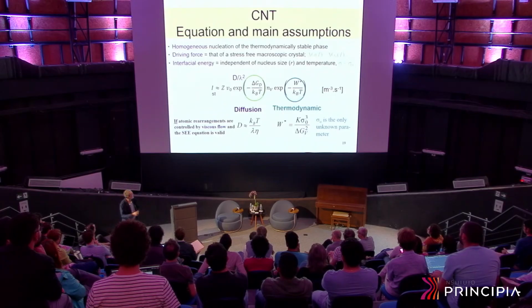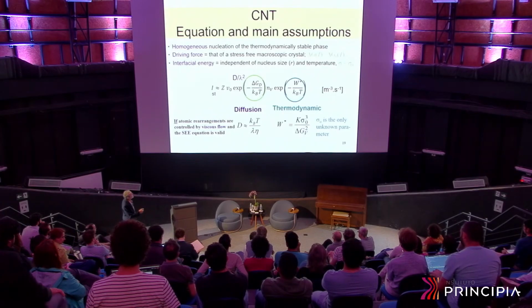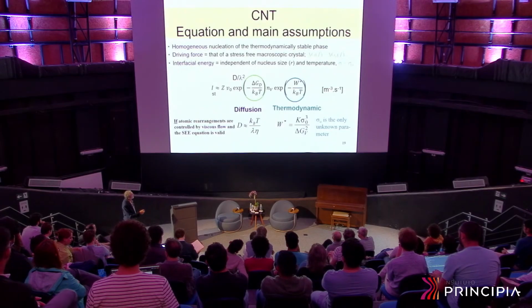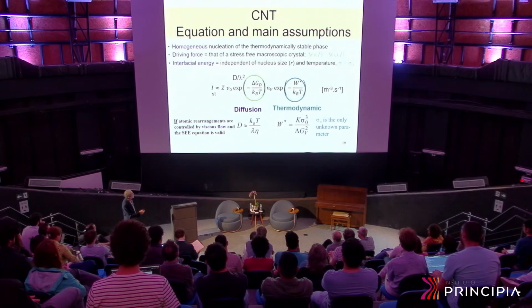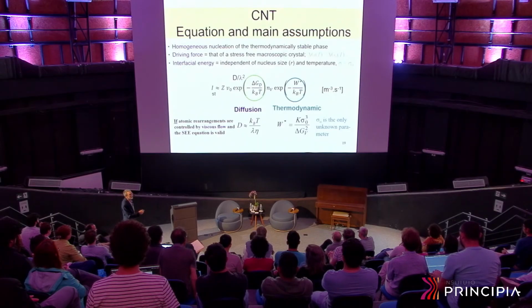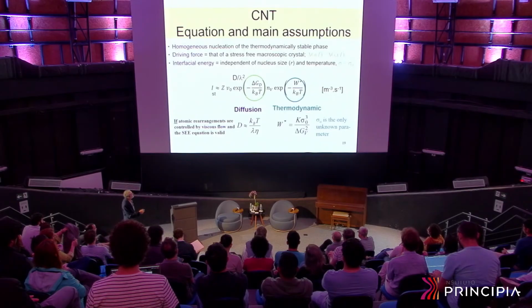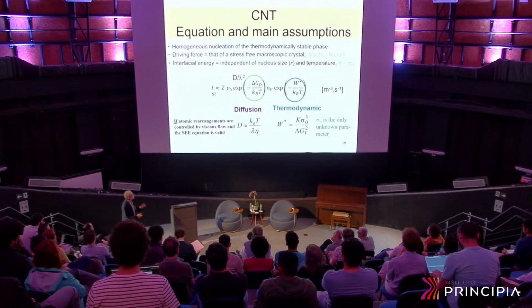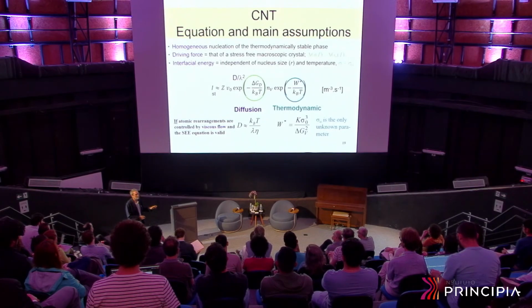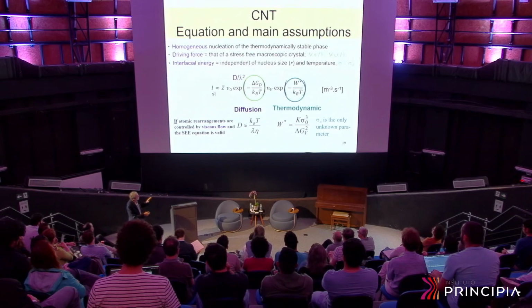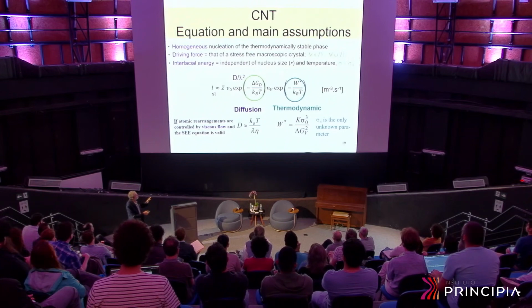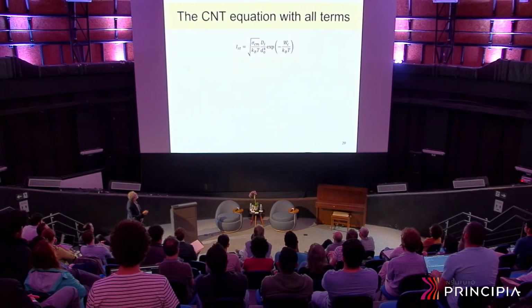With many things he did, he demonstrated that the diffusivity of molecules in a liquid is inversely proportional to the viscosity. This is kT, the jump distance, 1, 2, 3 angstroms, and this is the viscosity. So if you measure the viscosity, the diffusivity is inversely proportional to the viscosity. This is the Stokes-Einstein equation. So most people assume that this equation is valid in all situations, and then you can measure the viscosity of your liquid. This is easily measured in the lab, and then calculate the diffusivity. So we take care of this. We measure delta G by calorimetry. So we have only one adjustable parameter, and then you can test the theory.